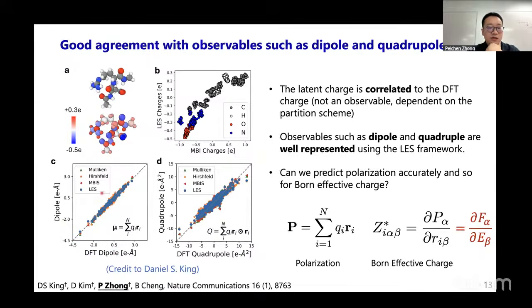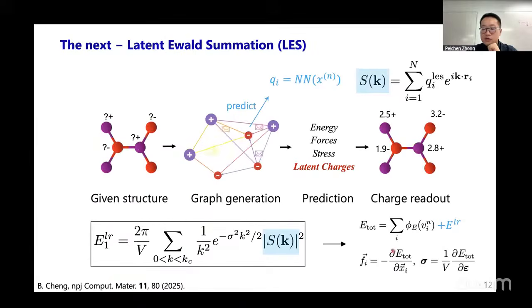Most importantly, the blue one is the machine learning derived latent charge, and the other three are the partial charges from DFT or conventional approaches. You can see that they basically show a very similar trend compared to the DFT. So that means if you believe the partial-charge-derived dipole is physical, as demonstrated in the conventional approach, then the machine learning derived charge is as physical as them. This is a very inspiring result: we can indeed use the energy and interatomic forces to derive or infer some useful physical quantities such as charge.